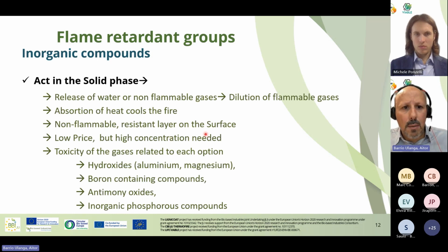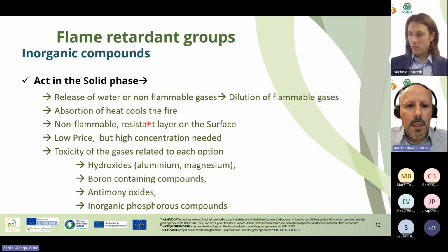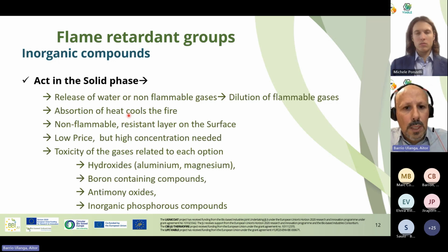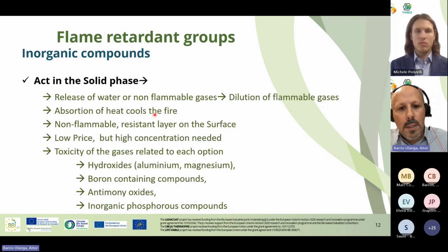In the case of inorganic compounds, as commented by Elvira, there are some inorganic compounds that capture the heat of the flame, so they dilute and cool the material, and they also release water when they have water of hydration, so they also dilute the gas in the combustion. There are some examples: aluminium, magnesium, boron, antimony oxide.